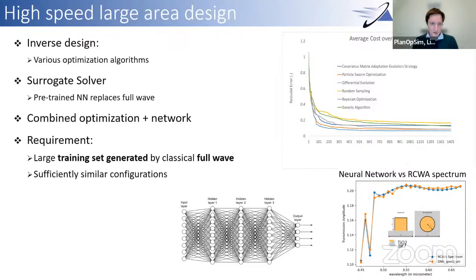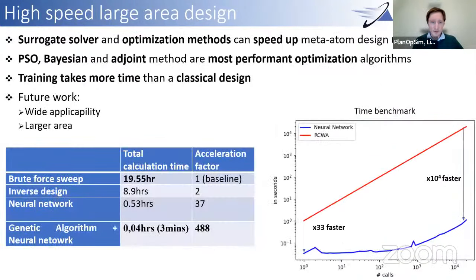And you need to stick to sufficiently similar configurations. But when you do that, we can get very good reproductions of the full wave calculation, but in a much faster time. And the good thing about these approaches is that they are essentially orthogonal. We can combine optimization with the neural network solution. And if we look at that then for a typical metasurface design project, where a brute force calculation might have taken 20 hours, combining the inverse design with the neural network, we can actually get that down to a couple of minutes or 500 times faster. That's already a great step.